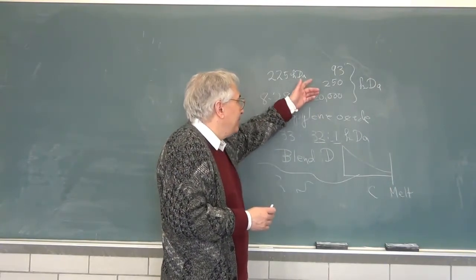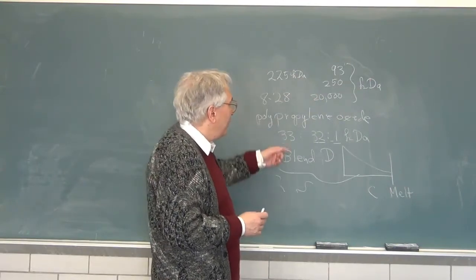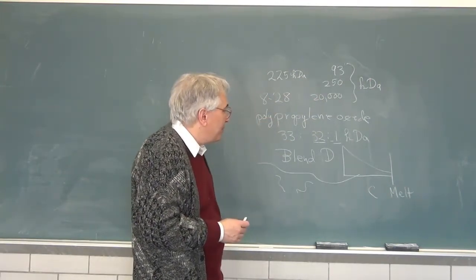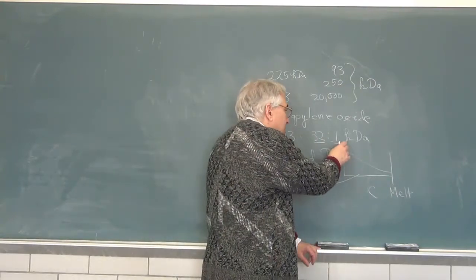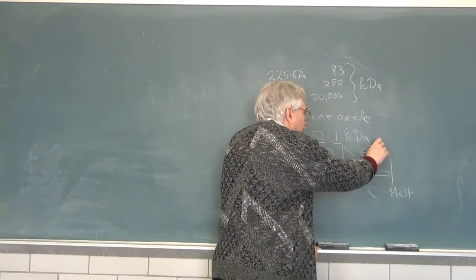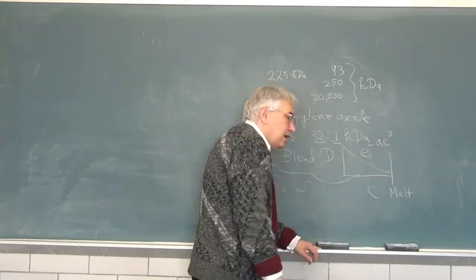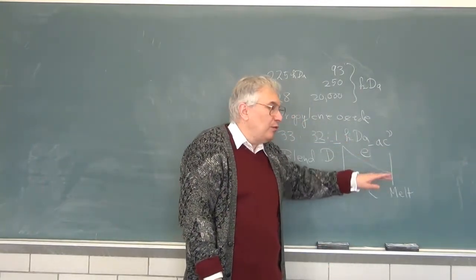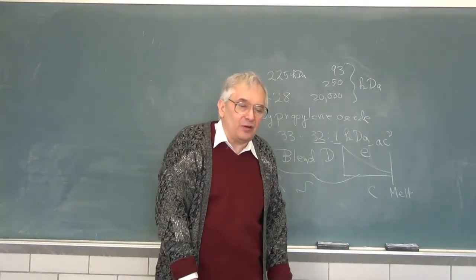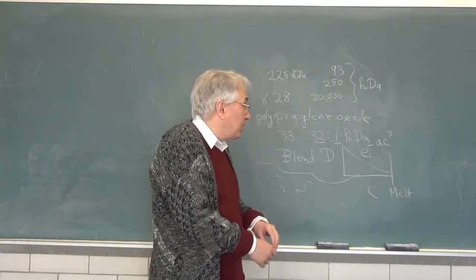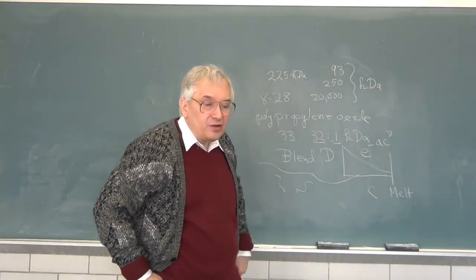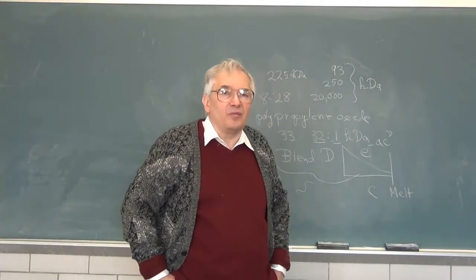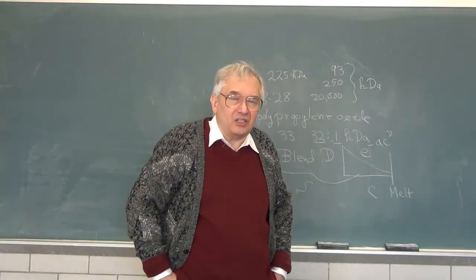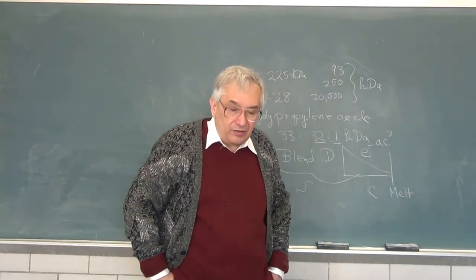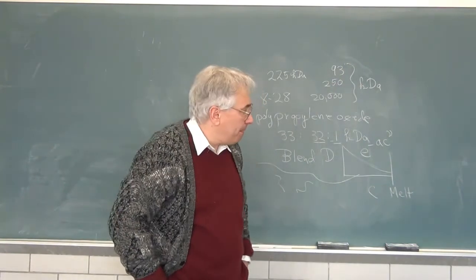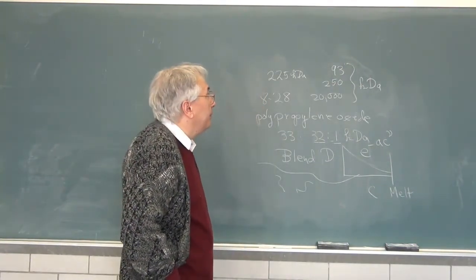However, the point of this is, we have a stretched exponential concentration dependence for D. It starts here, it ends up there, and absolutely nothing happens all the way out to the highest concentrations you can imagine, even with extremely large polymers. So we do have a fitting function description, a phenomenological description, which actually, at least in this case, works over a very wide range of concentrations. Okay.